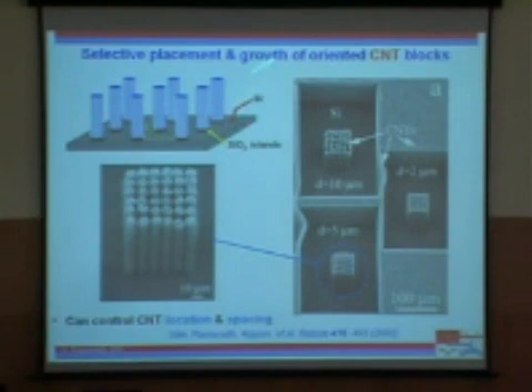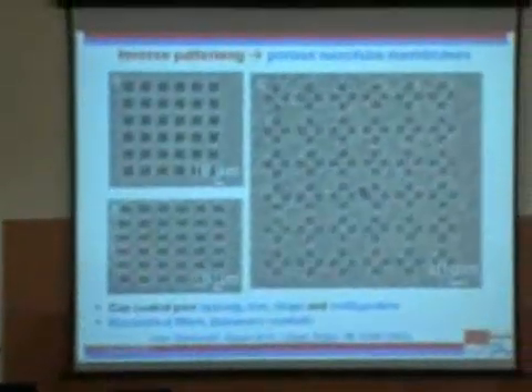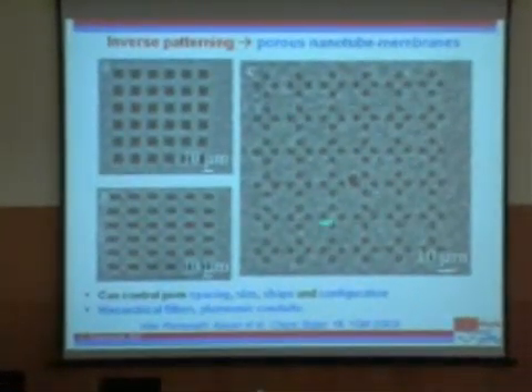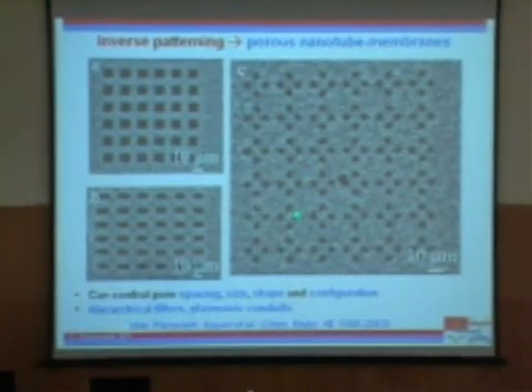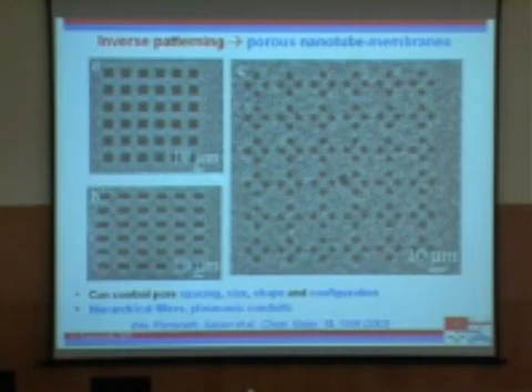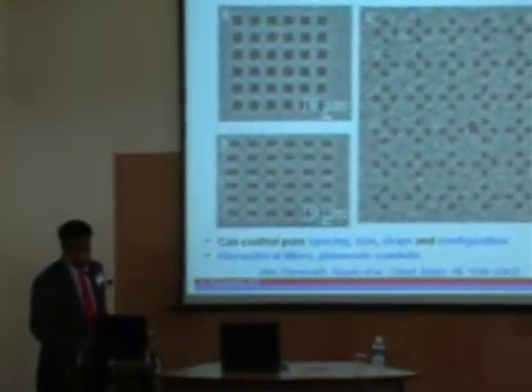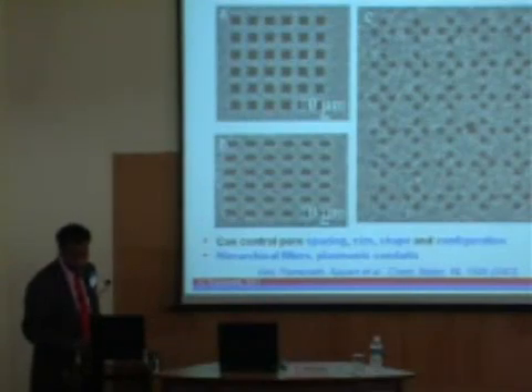These can actually be done by other methods also, for example, put down a catalyst, pattern it, and then do the growth. But here the beauty is, you just put the silica discs, and the catalyst and the precursor, everything comes from the gas phase. So all the design comes before the actual growth occurs. So it's very powerful. Now you can also make these inverse structures by just inverting the lithography. You can make these porous structures, which could be used for plasmonics if you want. You can control the sizes of these pores and the shapes and so forth, and they can also be used for a variety of applications in biology or membrane separation and so forth.